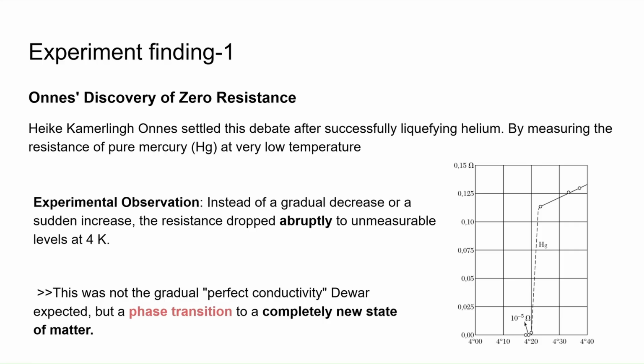The first experiment is Onnes's discovery of zero resistance in 1911. Heike Kamerlingh Onnes settled this debate after successfully liquefying helium, by measuring the resistance of pure mercury at very low temperature. At this low temperature, you will find that instead of a gradual decrease or a sudden increase, the resistance dropped abruptly to an unmeasurable level at 4 Kelvin. Just like you can see on the right hand side of the graph we show,